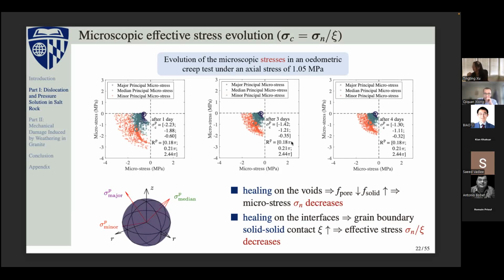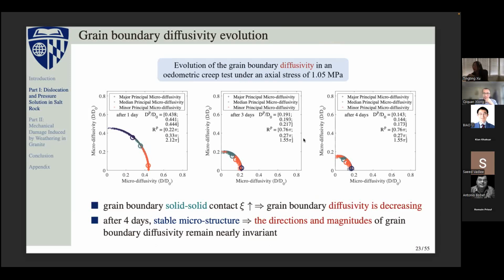So the local stress, or the effective stress, will actually control the behavior of the local inclusion and will therefore influence the global behavior. That is the first observation from the microscopic perspective. The second one is not the mechanical response, but the diffusion response. As I just said, because the solid-to-solid contact will increase, you can imagine that on the grain boundary, the diffusivity will decrease as time evolves. From left to right, you can see that the magnitude of the micro diffusivity on each contact decreases. Here we see that the solid-to-solid contact increases on the grain boundary. That is actually the limiting factor for these pressure solution mechanisms. So that tells us that this contact healing will prevent the pressure solution from continuing to happen. That is some observations from the laboratory and also some explanations from the microscopic scale.